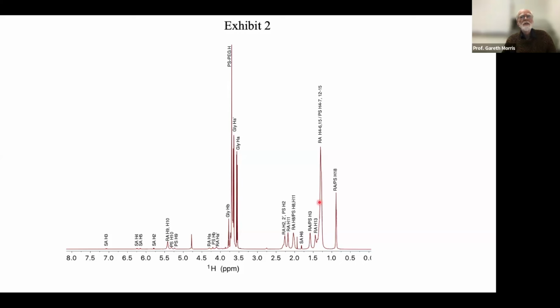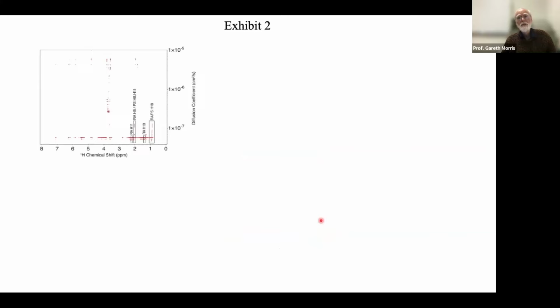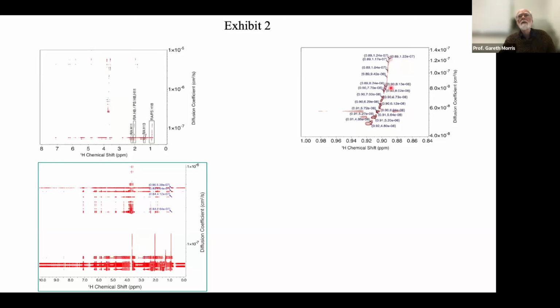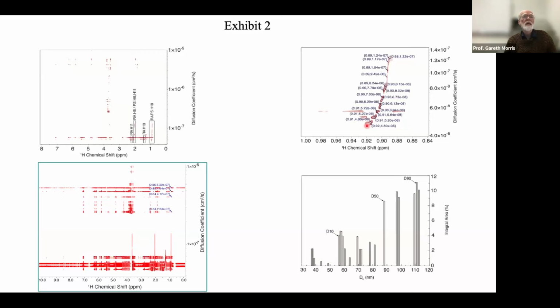down the garden path. And what we actually have here is two overlapping signals with different diffusion coefficients, one big, one small. And the result is that as we move across the unresolved profile of the methyl signal, the relative proportions of fast and slow signal are changing, and we get a smooth change in apparent diffusion coefficient that's just the result of two different diffusion coefficients, probably, just from the signal overlap. And we don't have a whole menagerie of different sizes of species. So be very cautious about software that promises you beautiful results. Much better to get an ugly result that you can trust.